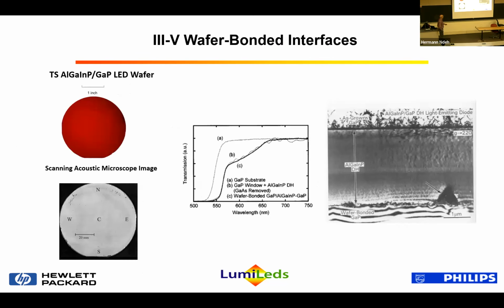So with that tool, we were able to develop capabilities, and this really shortchanges all the work that we did to develop the bonding, but we were able to scale this and develop the ability to bond 3-inch wafers over large areas. And so this is a transmission picture. Similarly, we looked very hard at what was happening at the materials. This is a scanning acoustic microscope image. The interfaces were nominally void-free. And we were able to develop the capability such that from an absorption standpoint, this is the absorption edge of the as-grown epi. And then similarly, post-bonding, you see that there's really no difference in the absorption in the bonded materials.